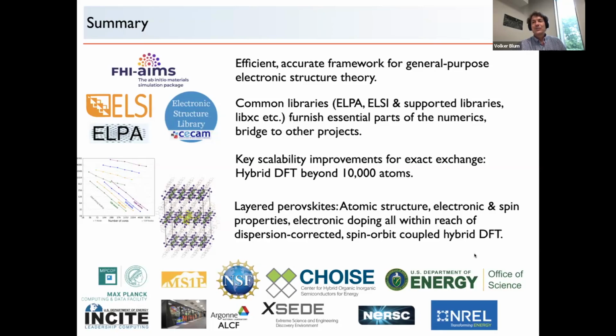Contrary to spin-orbit coupling, which on the energy levels has a big effect. So in the total energies, that effect remains manageable. But in the single particle levels, spin-orbit coupling really has to be included. And that's why spin-orbit coupling is critical for the energy band structures.